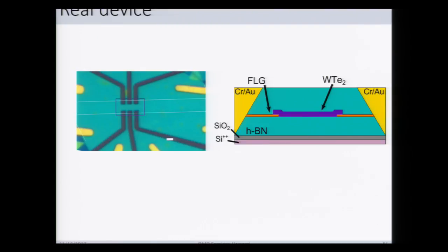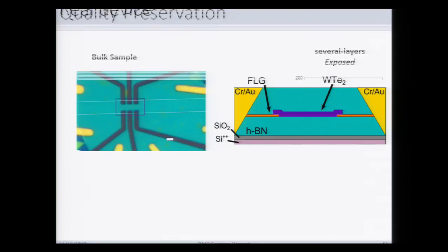Here is a cross-sectional schematic. What I didn't show in the previous stacking procedure is that we have graphite, few-layer graphite on both sides except for the central channel that is used as an electrical conduit that maintains a van der Waals seal in order to be able to continue measuring the device without having it degrade to air. So let's see if it works.